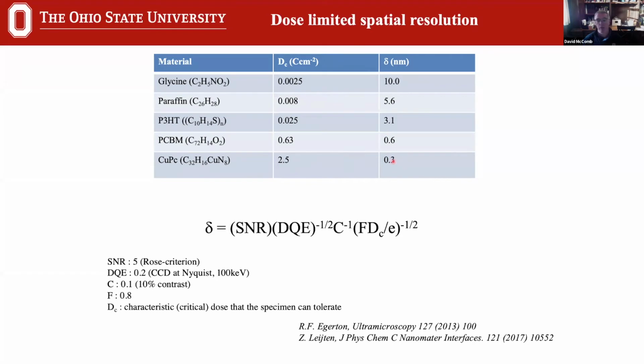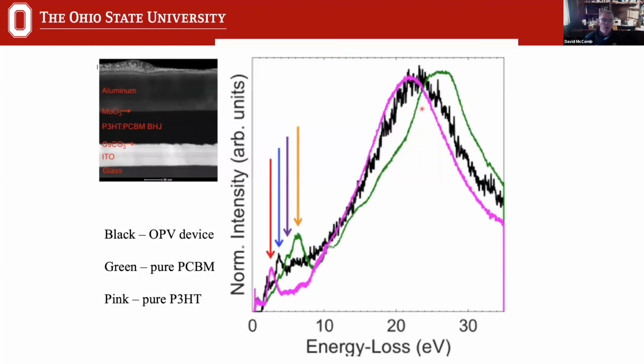So you can see, for example, in copper phthalocyanine, you should be able to get down to easily deep sub-nanometer, whereas in something like an aliphatic chain, like a paraffin or something, then you're going to be much more limited. So in Jessica's work, we were really looking, first of all, to see what we could see in terms of the overall blend here.